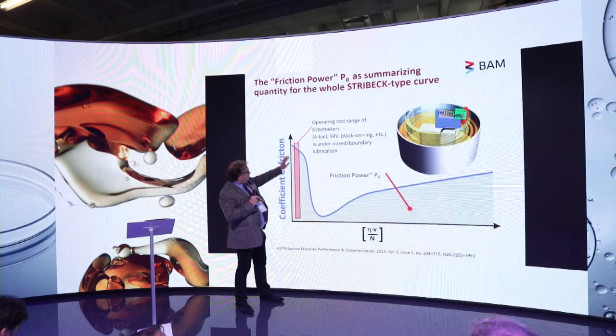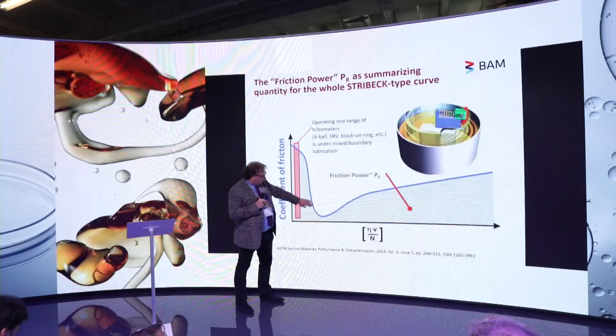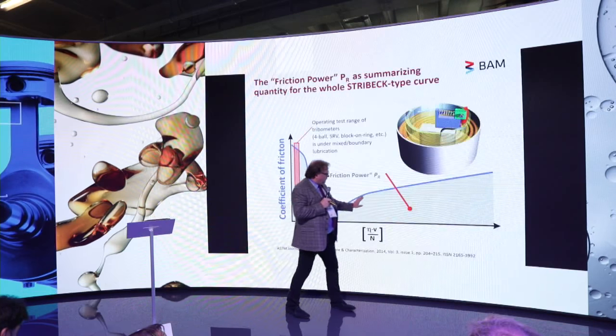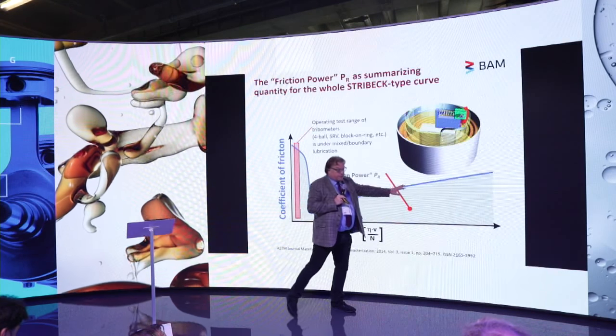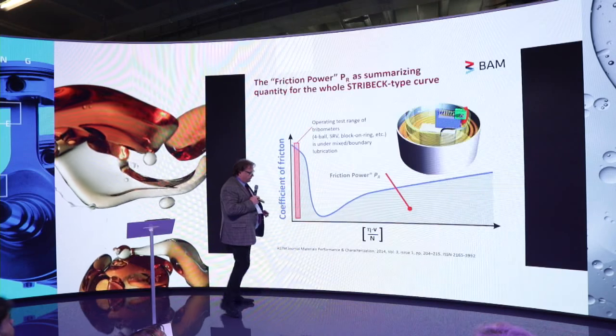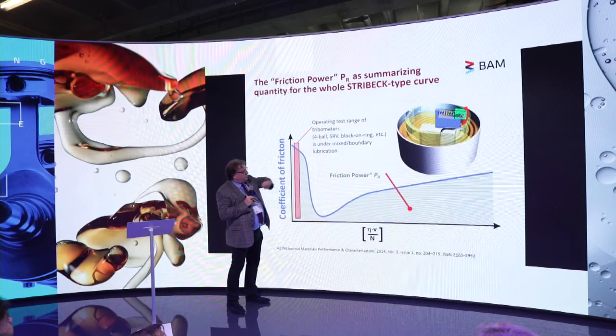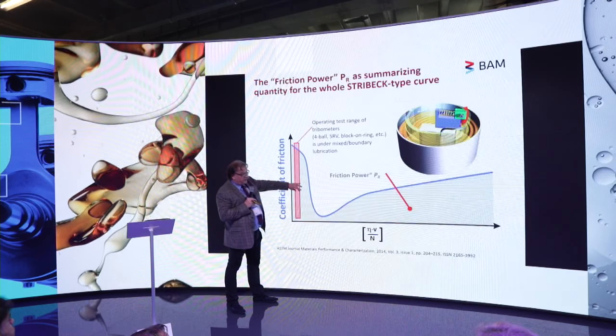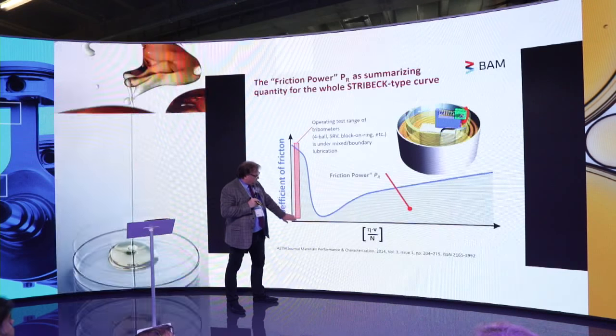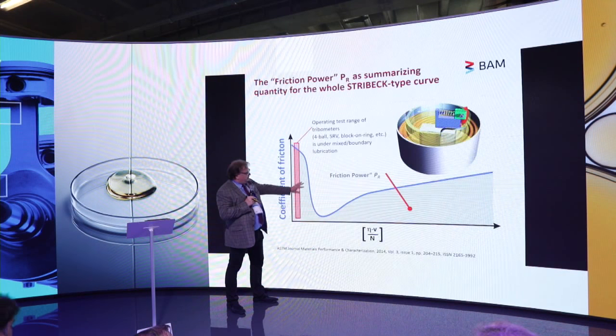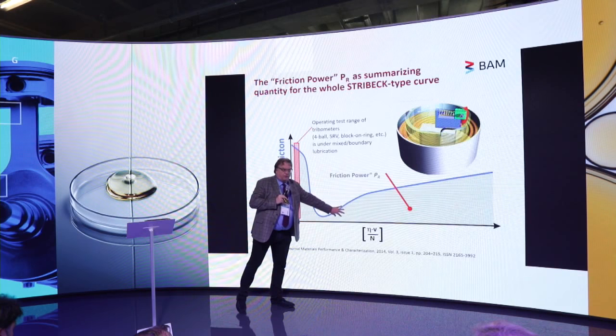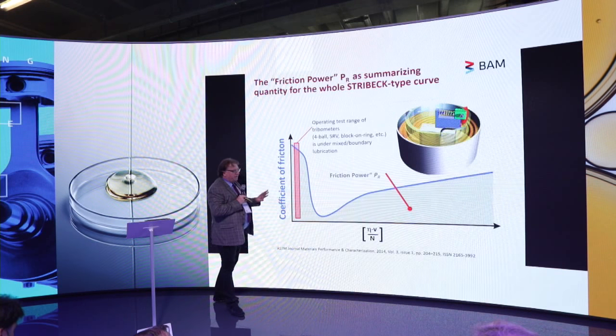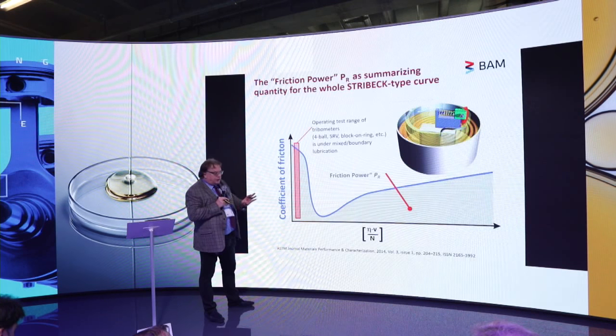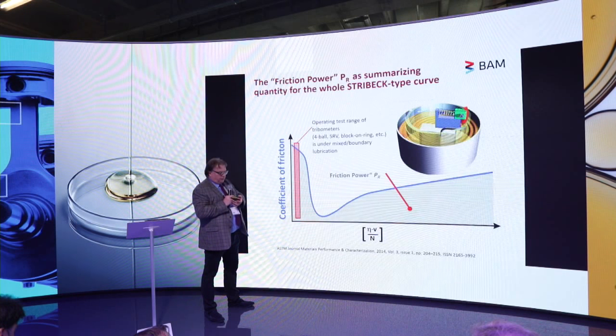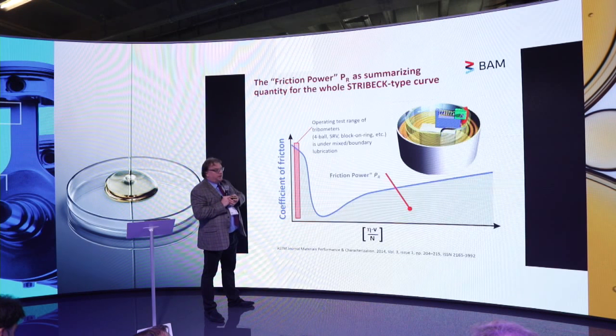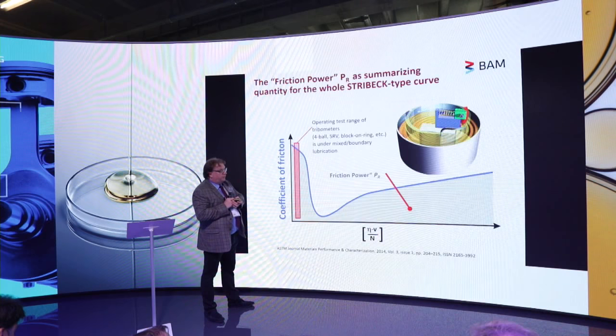When you start at low speed, you have high friction, it goes down, the film is formed, and then when you have the oil film, friction goes up. But those test machines only operate here at low speed. So it means all effects from viscosity are not taken into consideration, and I think this was a disadvantage, and maybe some development went in the wrong direction.